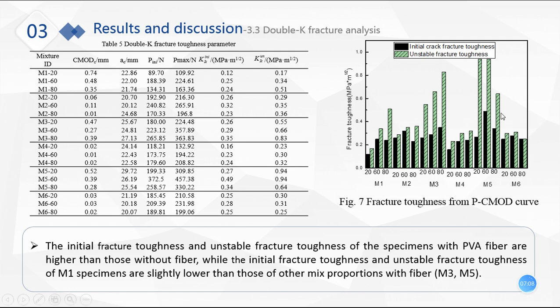Then the double K fracture toughness parameters are derived from the above curves, and the fracture toughness are shown in the right figures. We can find the initial fracture toughness and unstable fracture toughness of specimens with PVA fiber are higher than those without fiber, while the initial fracture toughness and unstable fracture toughness of M1 specimens are slightly lower than those of other mixed proportions with fiber.